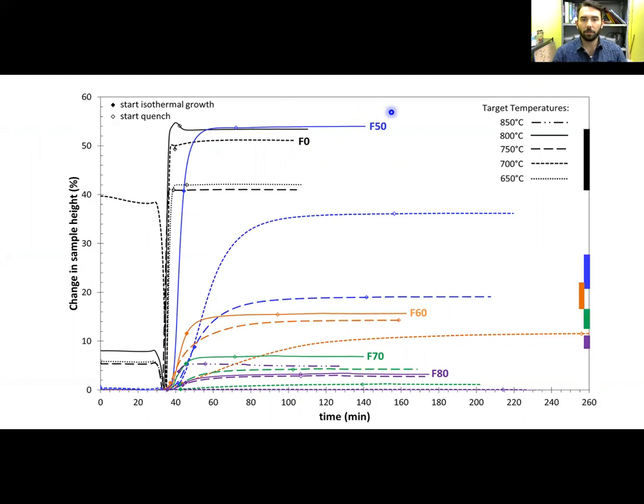To begin, we used the crystal-free sample F0 as a benchmark for vesiculation, undampened by crystals, which vertically expanded about 40 to 50% of its minimum height. The bars on the right represent ranges of inflation for crystal-bearing samples normalized for the glass content, since of course melt and bubbles are changing volume, not the crystals themselves. In other words, these bars represent the expected range of inflation for each crystal content. And we can divide this plot into two segments.